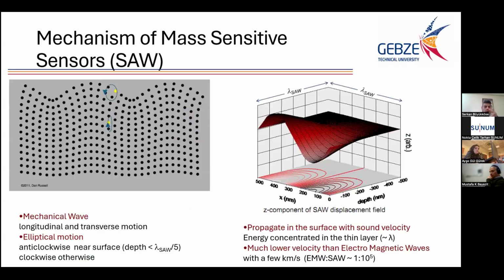If you look at more details of the acoustic waves, generally they are, of course, mechanical waves with longitudinal and transverse components. But it should be noted that in the case of a piezoelectric substrate, it's not only a mechanical wave, because there is also an electric potential wave accompanying the mechanical wave. It's sometimes important for sensing applications, but in our case, the dominant mechanism is the mechanical interaction. So I'm not talking about this electrical wave, but it's not only a mechanical wave in the case of piezoelectricity.